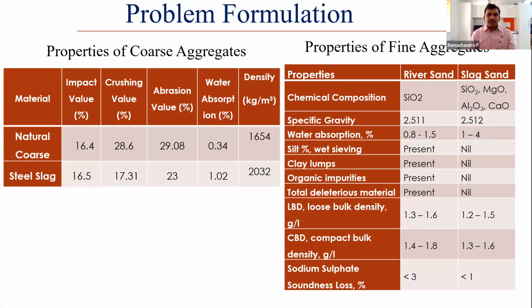These are the properties of coarse aggregate as well as fine aggregate. We can see the coarse aggregate values: impact value, crushing value, abrasion value, as well as those of steel slag. One point to note here is the density, which might be a little bit of a task: the steel slag density is 2032, whereas the density of natural coarse aggregate is 1654 kg per cubic meter. This is one thing we need to take care of, due to the metal waste from the heavy iron ore. So the steel slag coarse aggregate density is more compared to natural coarse aggregate.